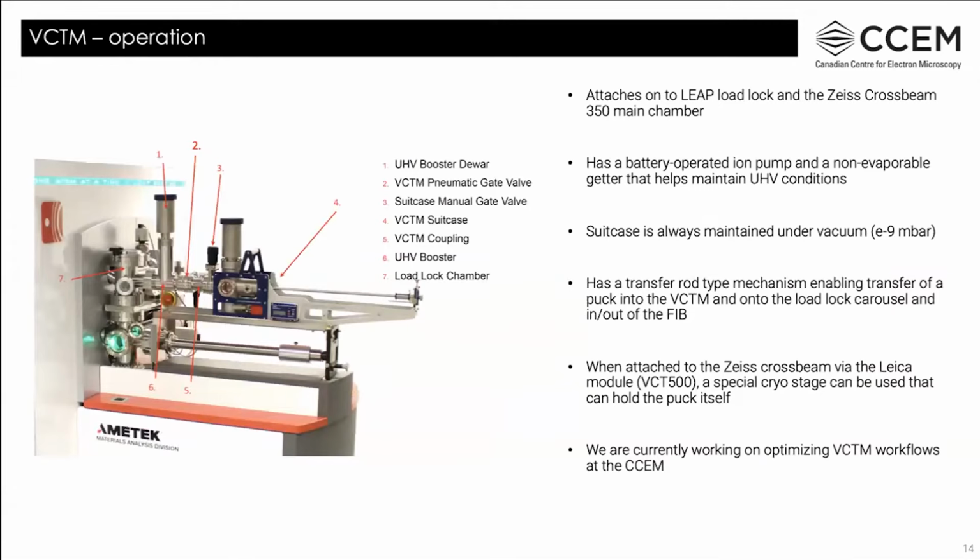I'll briefly go over the VCTM operation. The suitcase attaches onto the load lock of the LEAP through a coupling that needs to be pumped down before the valves between the suitcase and the load lock are opened. The suitcase is pumped down using a battery-operated ion pump and a non-evaporable getter, and it's cooled to cryogenic temperatures